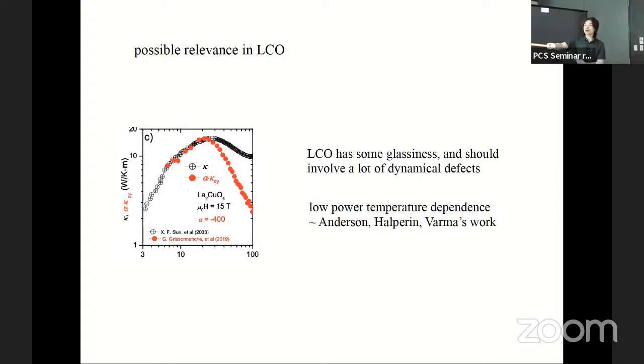Moreover, if we look at the low temperature longitudinal conductivity, the black dots, you can see that it's not T cubed. The power is smaller than T cubed. And that is also a feature that is compatible with Anderson, Halperin, Varma. So maybe there's some kind of defect that makes the phonon longitudinal transport a lower power than T cubed. So that's some evidence that maybe we really should consider dynamical defects in LCO.